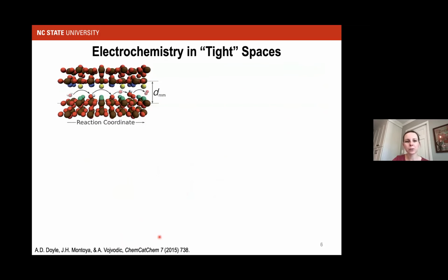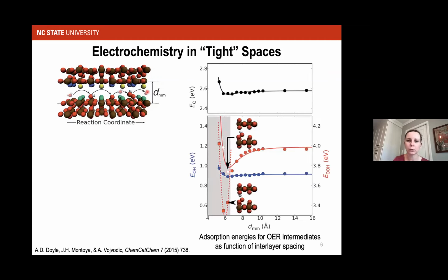From an electrochemical standpoint, similar benefits could be realized. And this is an example from the group of Alex Vojvodic at Penn, where they simulated what's going on if you take 2 sheets of ruthenium oxide and studied the oxygen evolution reaction occurring under confinement, so water molecules going to form oxygen gas as a function of the interlayer spacing between these 2 sheets.